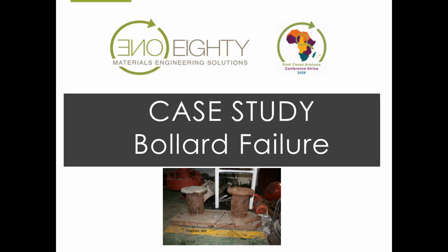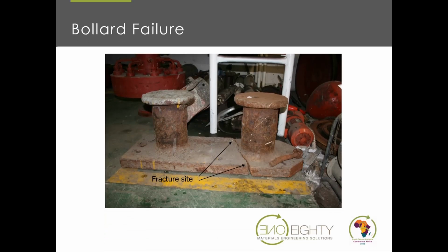So this resulted, in fact, in a casualty. It was a bollard on the dock at the Oceana facility in Saldanha. The vessel was tied up alongside, and they were pumping fish into the catchment area for processing. In the process, the bollard fractured, and that resulted in the death of the chief engineer, which was quite tragic. The matter went to court because the wife of the chief engineer made a case against Oceana, and also the harbor or quayside owner, for damages.